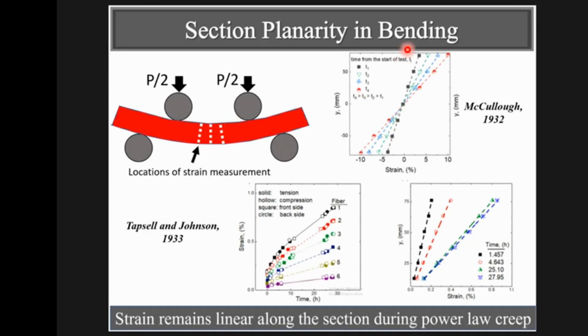First of all, they established that the strain was linear across the cross-section, even though the stress and strain are no longer linearly related. This is power law creep. They established that after a primary stage, if you look at the strain, it reached a steady state. That is, the strain increased linearly with time.